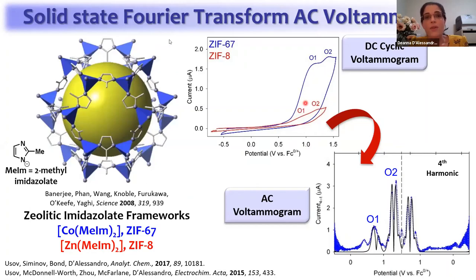But one of the issues with high capacitance is it's very difficult often to see the Faradaic processes. So if we use Fourier transform AC voltammetry, which is simply applying a sinusoidal frequency across the potential ramp, what we find is a little bit like NMR spectroscopy. The Faradaic processes simply fall out, and we can actually observe them very clearly using the AC experiment and even model the kinetics of the charge transfer. So this has been a really important technique to sort of complete our toolbox, if you like.